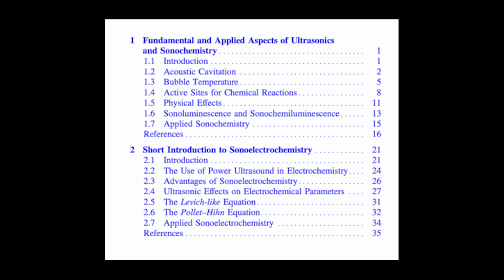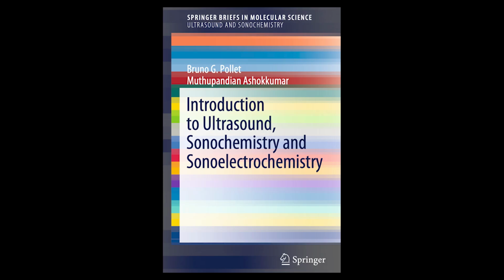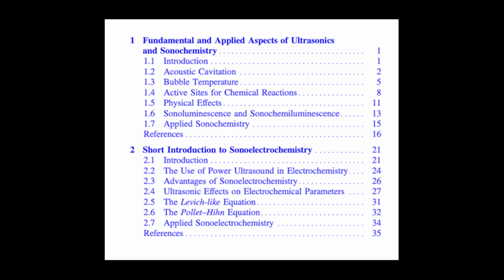This is where some really elegant chemistry comes in. One of the classic methods, pioneered by Henglein back in the 80s, used methane gas as a kind of molecular thermometer. How does that work? It's brilliant. They dissolve methane in water that was saturated with argon gas. Argon doesn't react much. Methane is volatile, so it easily gets inside the bubbles as they form and grow.